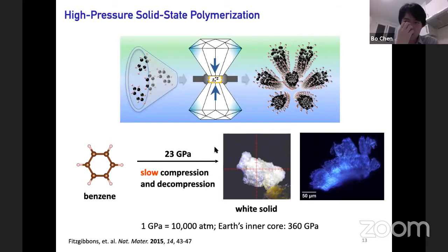So this reaction, we think it's a kinetically controlled process, the polymerization. So there are many potential pathways from benzene to other polymers. If we increase the pressure slowly, we are able to follow only one or two pathways, and that's going to give us an ordered product. If you compress too fast, many pathways will be followed. So you will end up with an amorphous material.